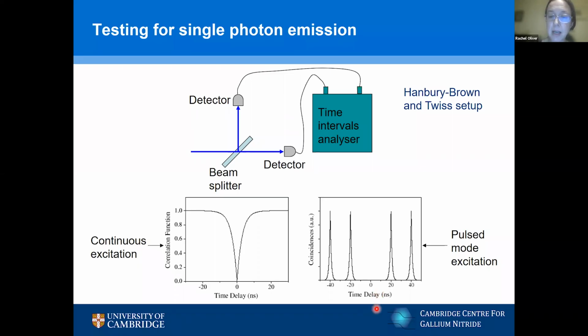And for the button presses at these 20 nanosecond intervals, we shouldn't have a photon for a particular button press arriving at both detectors simultaneously. So again, we've got a missing pulse at time equals 0. But we could have a photon arriving for one pulse and then for the next pulse 20 nanoseconds later. Or we could have one arriving at the other detector 40 nanoseconds later, corresponding to a gap of 2 pulses. So here, the lack of a pulse at a delayed time of 0 is our signature of single photon emission. Okay, so you'll see traces a bit like that throughout this talk.